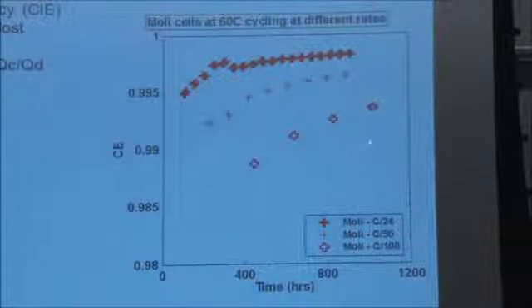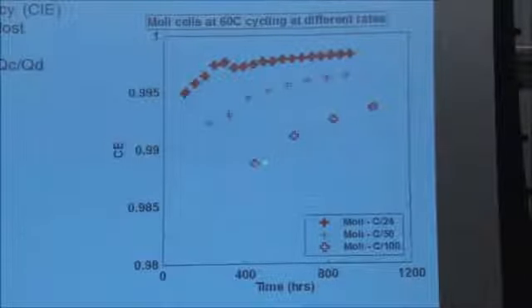And obviously, if it takes 200 hours for a cycle, you're going to get a data point every 200 hours in these bold crosses. If it takes 100 hours for a cycle, total cycle at C over 50, you get a data point every 100 hours, okay? So you can notice that the Coulombic efficiency of these cells depends on the charge-discharge rate. And the reason for that is it takes longer for a cycle, which means there's more time for the parasitic reactions to take place when you go slower.